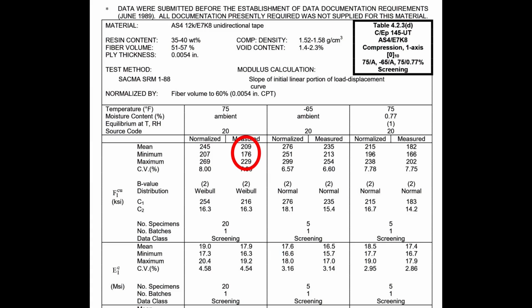Now if you have a look at the database, you see there's a wide range of test examples included, all tested to failure under either uniaxial tension or uniaxial compression. But if you look at some of the data sheets, you see very much lower numbers. So taking one at random here for an AS4 unidirectional carbon fibre laminate, there's a range of failure stresses, and the low number being 176 KSI, and that's about 55% of the value which Spencer Composites use for design.